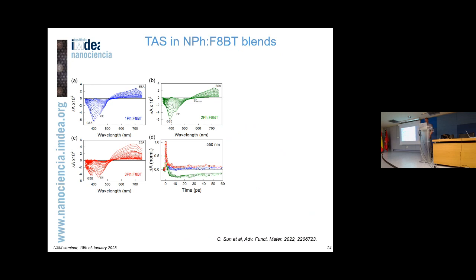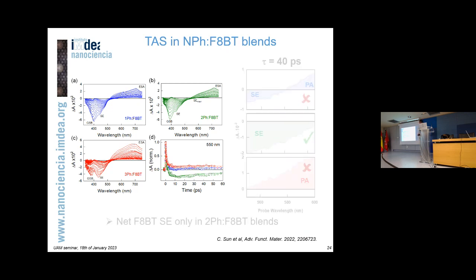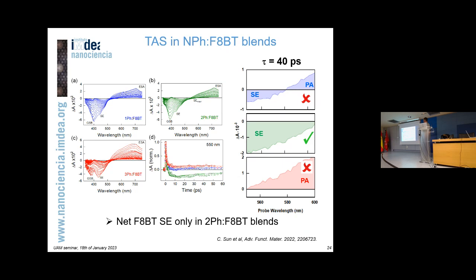So again, we came back to transient absorption experiments. These are transient absorption spectra taken at different delays for blend number 1, number 2, number 3. You probably don't see very well the difference, but the main difference is here. If you zoom up, you can see that in the region of interest, for the second blend there is stimulated emission. For the first blend, you have a sort of mixture. And for the third blend, you have only excited state absorption.